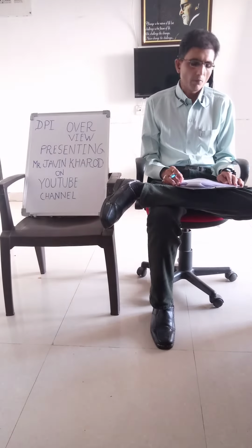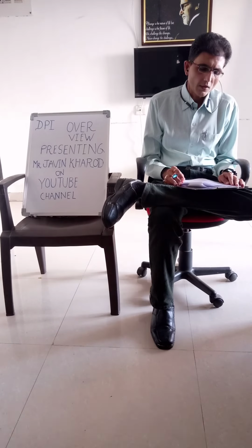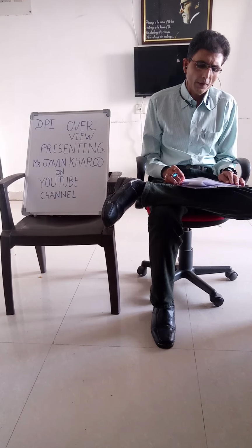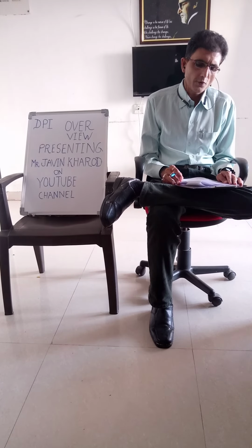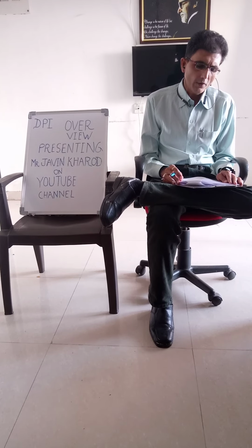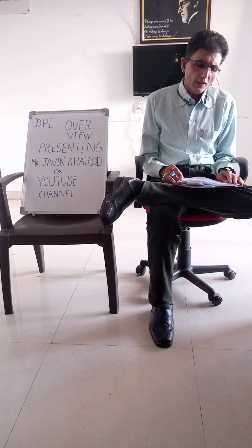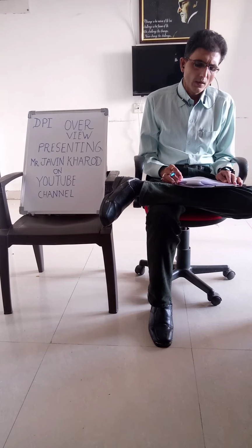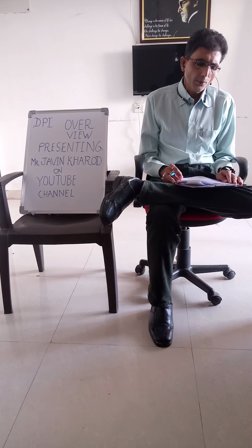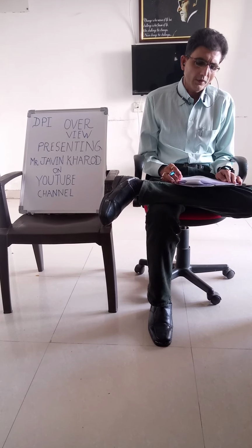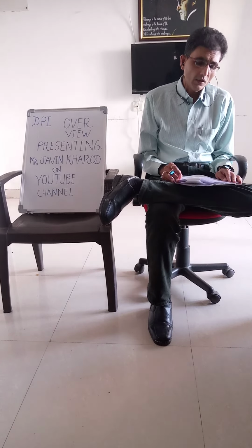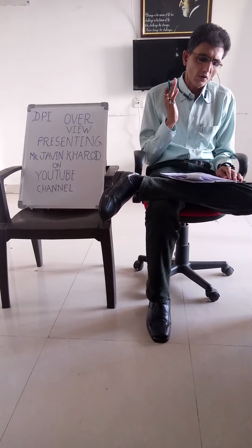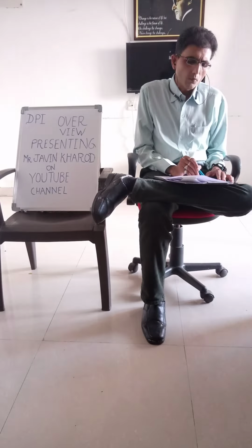Excess penetrant removal. The excess penetrant is then removed from the surface. The removal method is controlled by the type of penetrant used: water washable, solvent removable, lipophilic post-emulsifiable, and hydrophilic post-emulsifiable are common choices. Emulsifiers represent the highest sensitivity level and chemically interact with the oily penetrant to make it removable with a water spray.